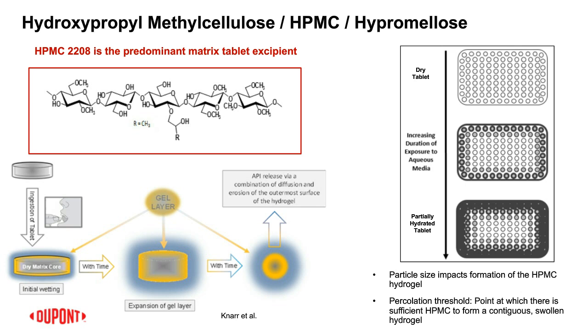And why is this so important, right? So when this tablet is administered, on the right-hand side, I leveraged this slide from Matthias Knarr, one of my teammates in Germany. But once this is administered, the tablet is swallowed, hits the gastrointestinal or the gastric media first of the stomach. That is an aqueous media. And those particles of HPMC that are on the outermost surface of that matrix tablet, they begin to hydrate. They begin to swell, and eventually they coalesce together to form this swollen polymer hydrogel, if you will, this matrix polymer hydrogel that envelops the matrix tablet core.